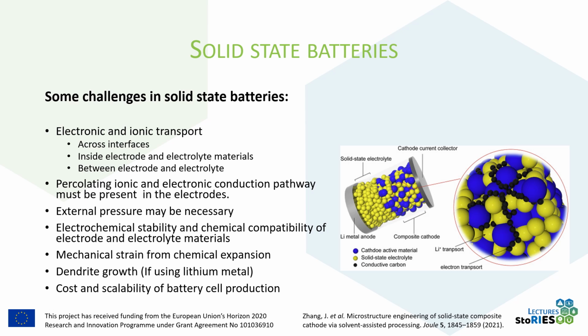Contact and transportation issues also mean that a solid-state battery cell may require an external pressure in order to operate optimally. The external pressure helps to decrease the interface resistance. As in a conventional lithium-ion battery, the electrochemical and the chemical stability of the components is crucial. Solid-state batteries are much more susceptible to mechanical strain, for instance from chemical expansion from lithiation and delithiation. Again, the interface resistivity and the transport properties are critical.